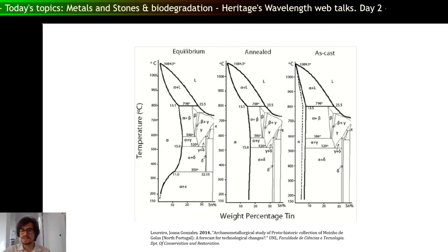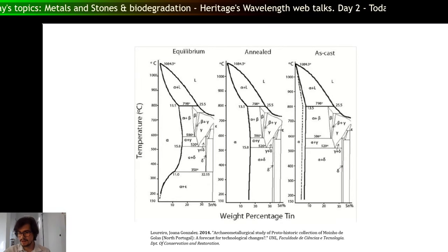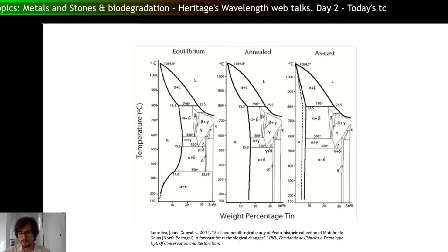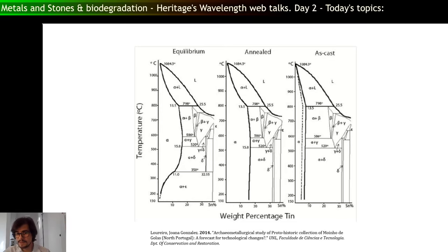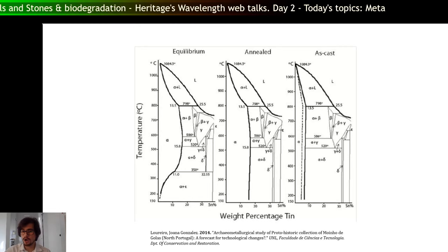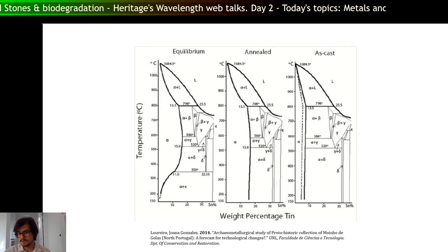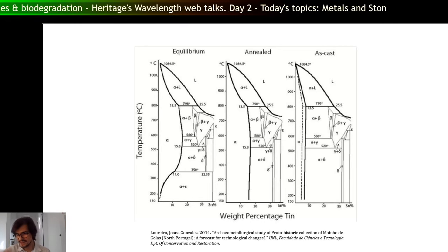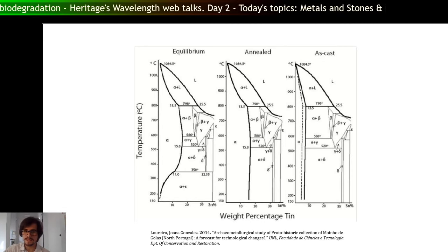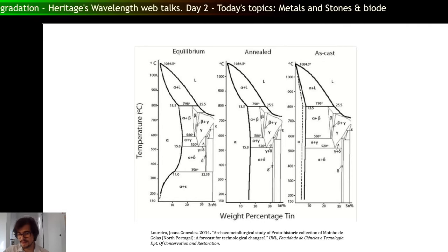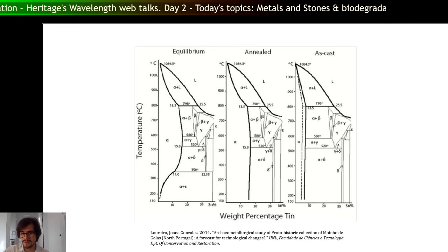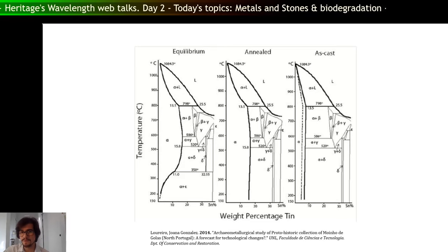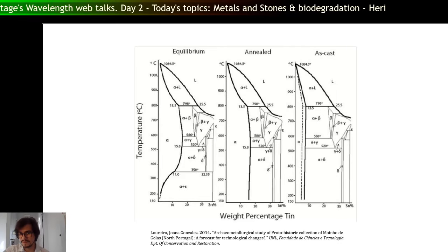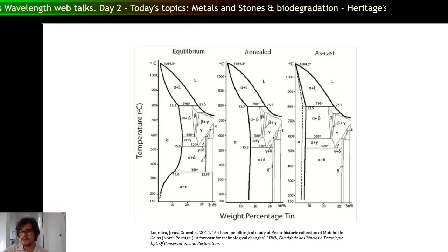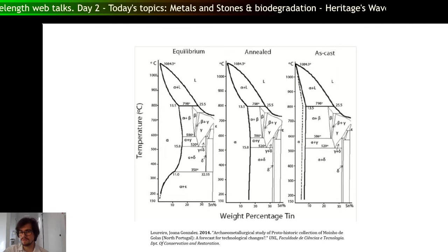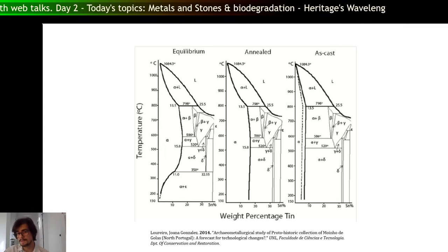Another phase diagram, just forget the middle of it, which is hellishly complicated, and focus on the bottom part. This represents the phase diagram of a copper-tin alloy, which we saw before in the beginning, but in more brief detail, just the first part. You can see in the middle one, annealed. So let's look at 10%, an alloy with 10% tin. In theory, an annealed one with 10% tin, if you look at the microstructure, you will see only this alpha phase here. You have one homogeneous phase.